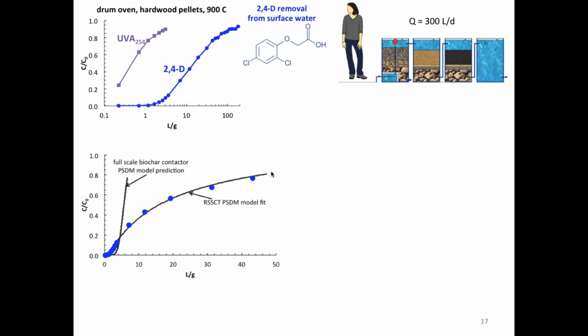So what I'm showing here, these dots, these are column data. They're the same column data as shown in the graph at the top left, but I've just changed the axis from a logarithmic axis to a linear axis, and then fit those data using the pore surface diffusion model, that mathematical model I was referring to. And then when I consider the operational parameters of the full-scale system and using that model fit, I can generate a predictive curve, which is the curve to the left where it says full-scale biochar contactor PSD and model prediction. That is what the pore surface diffusion model predicts would be the breakthrough curve for the 300 liter per day blue barrel biochar system.